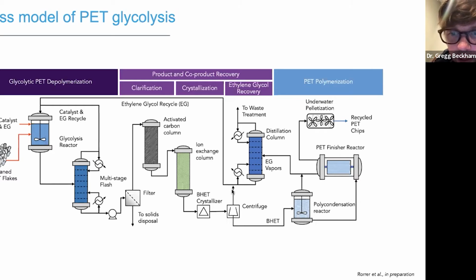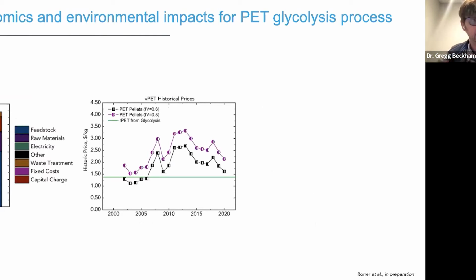And then separately, the liquid from the centrifuge will go through a distillation column. You'll remove excess water, and then the ethylene glycol at the bottom of this column can be recovered and recycled to the reactor. And so here are the economics and the environmental impacts for this glycolysis process, or the predicted ones at least. So this is recycled PET from this PET glycolysis process, the minimum selling price. And you can see immediately that more than half of the minimum selling price is the feedstock. And so if you can access feedstocks beyond clean PET flake, this is a very conservative analysis with a substrate that we can buy today at scale, which is clean PET flake. But if you can imagine reducing this dramatically, like for carpet or waste textiles, where this will be almost zero, you can see that the overall minimum selling price will be reduced dramatically.